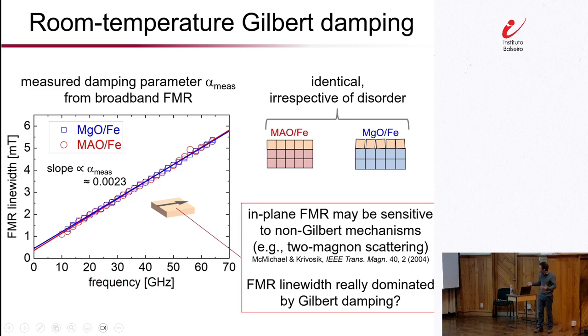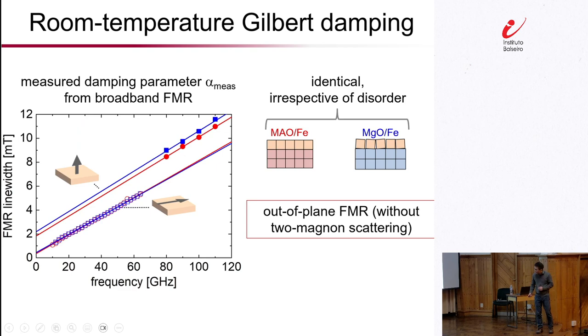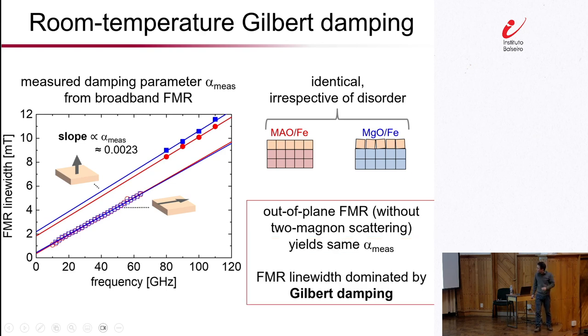So it's actually a very important, legitimate question to ask ourselves: is what we're observing actually dominated by Gilbert damping? Fortunately, there is a nice workaround. It turns out, again without going into a lot of gory explanations, that when we have the film magnetized out of plane, we can suppress this pesky, annoying two-magnon scattering process, the T2-like relaxation process. So even here, what we observe is that the slope is indistinguishable, identical among the two samples and between these two measurement geometries. So at this point, we can be quite confident that what we are measuring here, the slope of line width versus frequency, is indeed dominated by Gilbert damping.